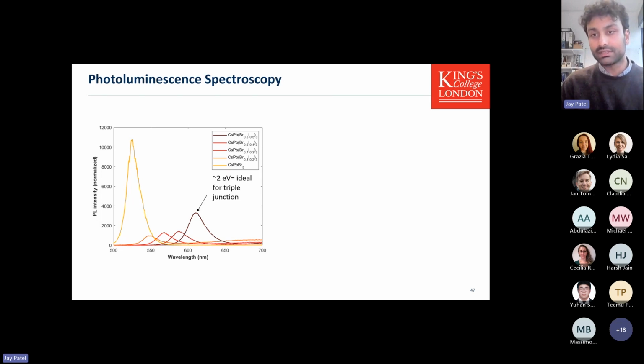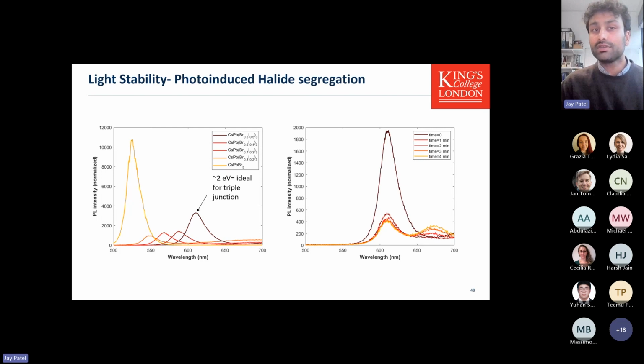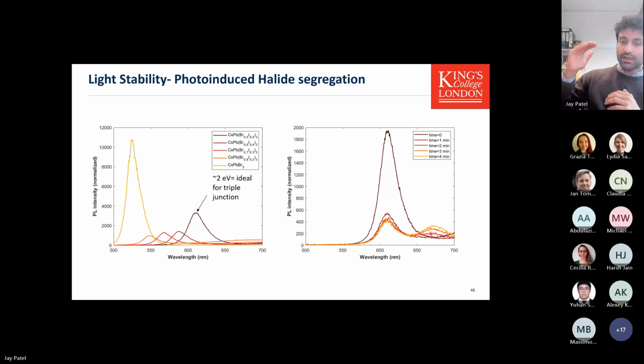And how good is this material? Well, if you zoom in on it and scan for a longer period of time, you start to see a shoulder that appears on the very right of the spectrum. What that shows is that there's a new material forming, emitting at a longer wavelength. And as I said earlier, anything that doesn't emit from the wide band gap is somewhat of a trap or another state that reduces the voltage. And that's something you don't want.